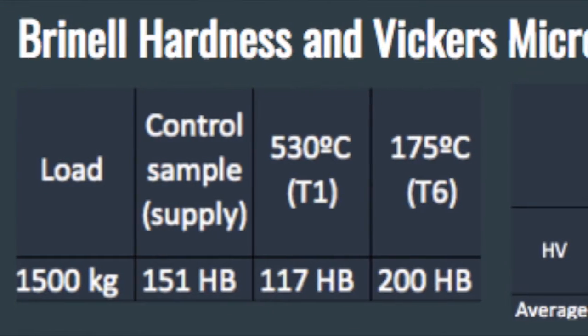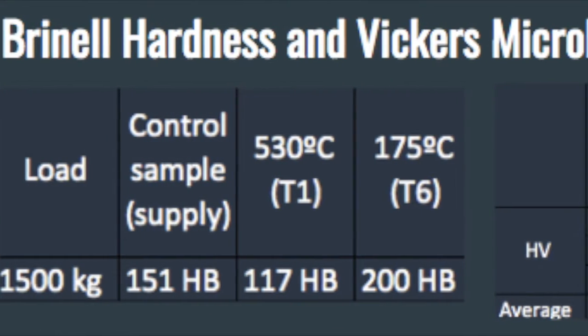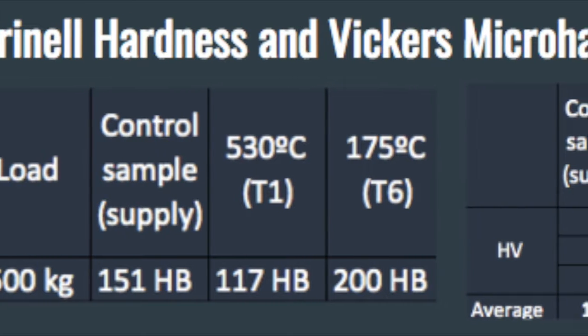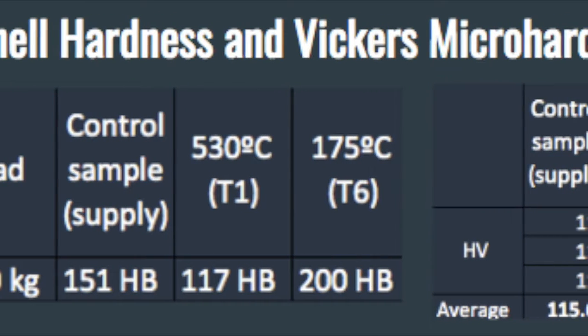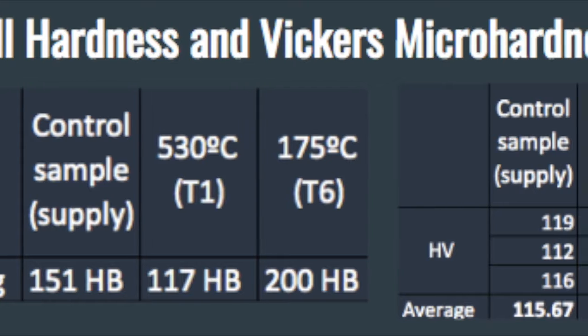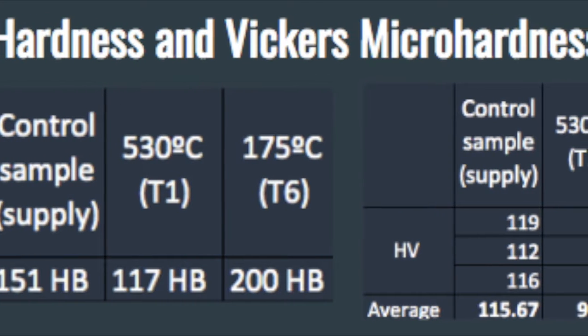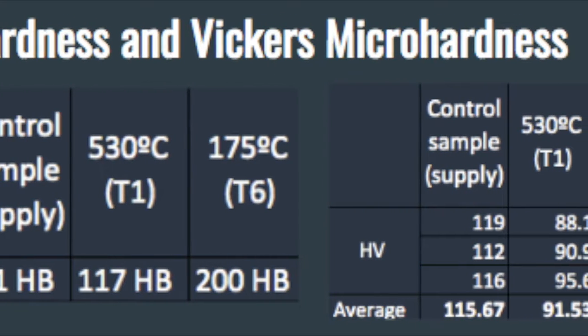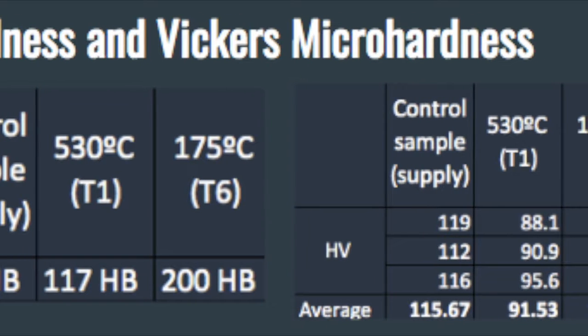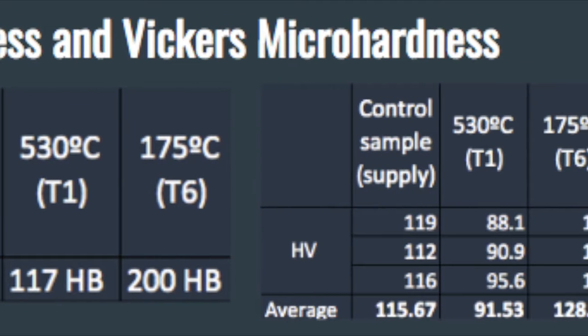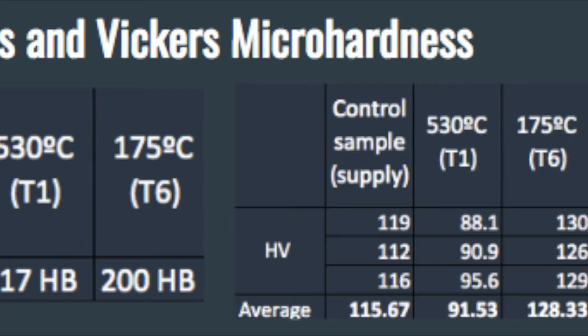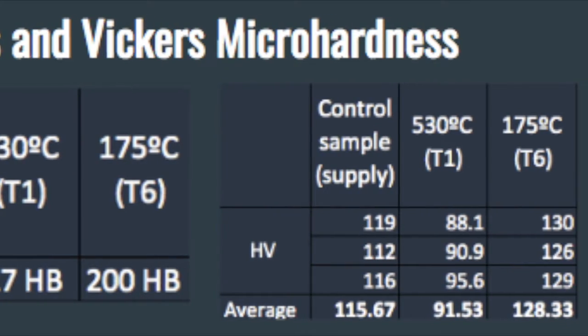In the table, we can see the results obtained in the Brinell and Vickers hardness tests for the 3 samples: the control sample, the one that was heated to 530 degrees, and the one that was reheated to 175 degrees. For the Vickers test, we did 3 tests on each sample, and we obtained an average.